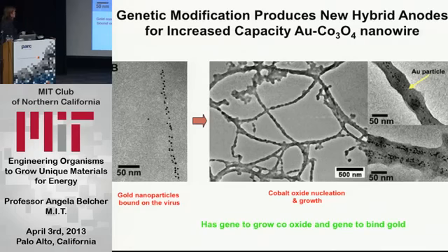And so this is a TEM micrograph of the virus that has gold nanoparticles across it, and all the spaces in between that you can see, or where it has the proteins that grow cobalt oxide. And so the ones that have the gold are supposed to grow gold. And so then he gives it cobalt oxide, and it kind of zips it up, and now you have this hybrid material that's a cobalt oxide gold hybrid material, and it has the gene to grow both.